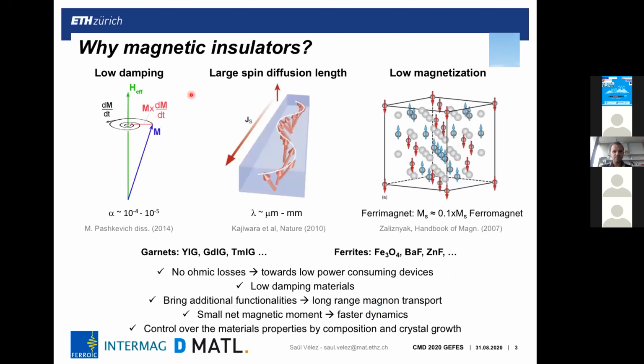But the question is why we would like to work with magnetic insulators. The first thing to think about is that we have many materials, such as garnets, in which the damping is very low, comparable to permalloy. And if you compare with cobalt, the damping is much lower in these materials, meaning that the dissipation in such devices would be much smaller. Also, because they exhibit very low damping and are insulating, they can enable new functionalities, for instance the propagation of spin waves, in which you can electrically excite and propagate spin information in the form of spin waves in the material.